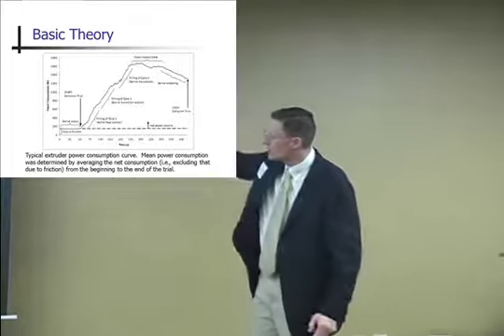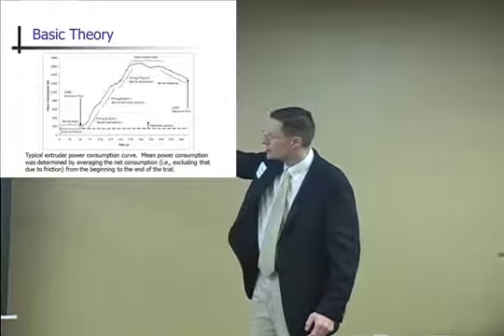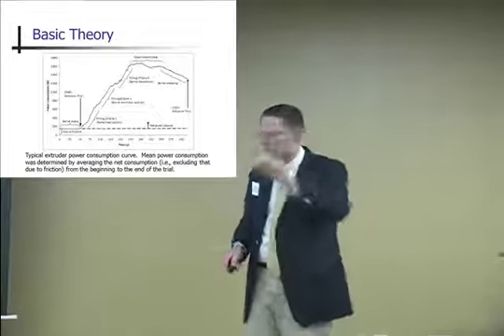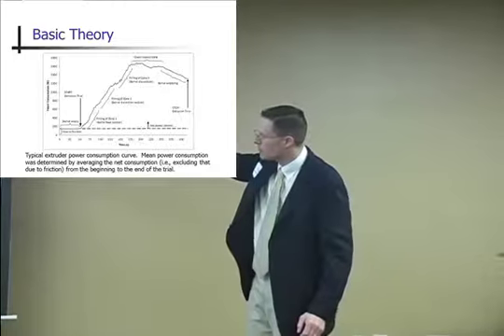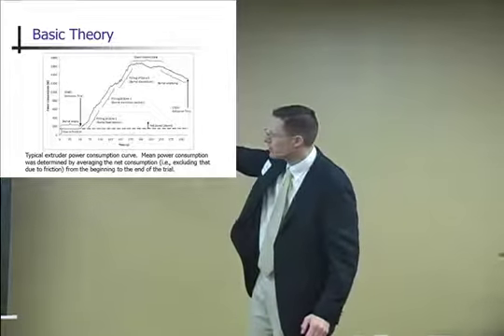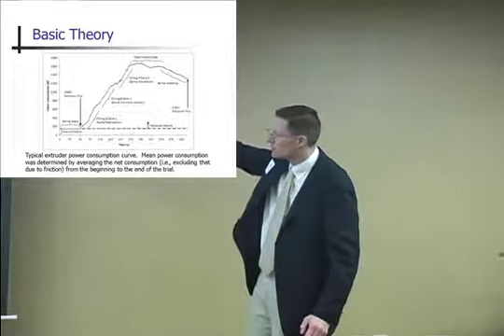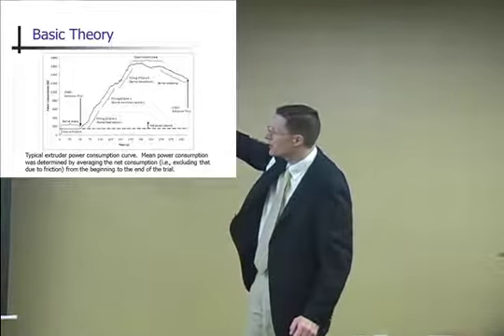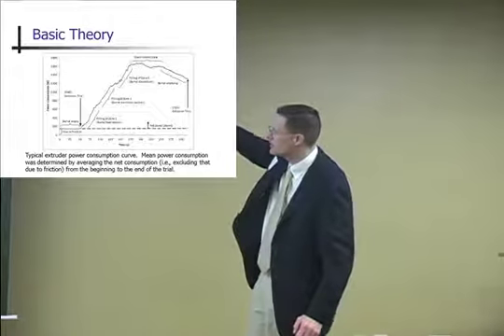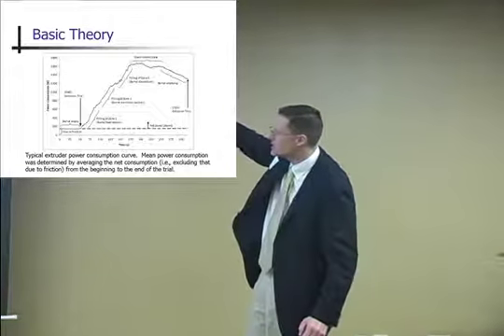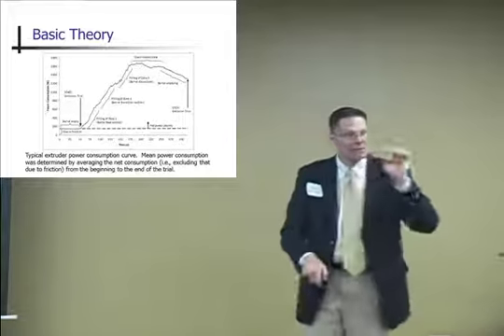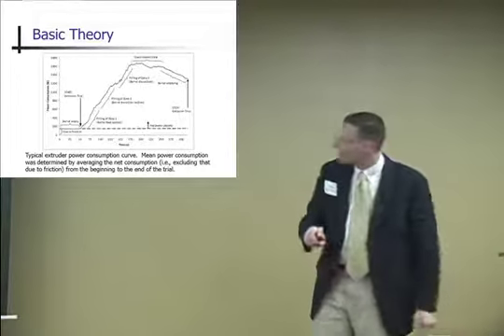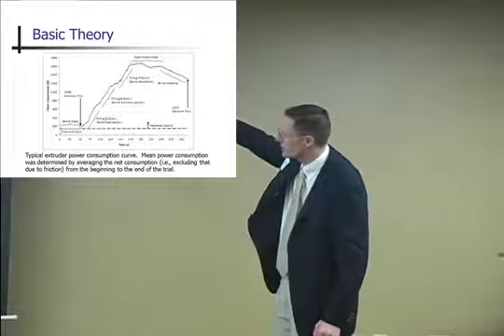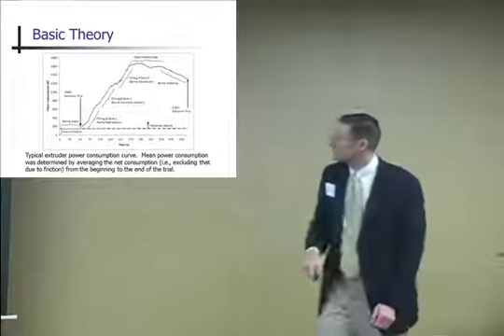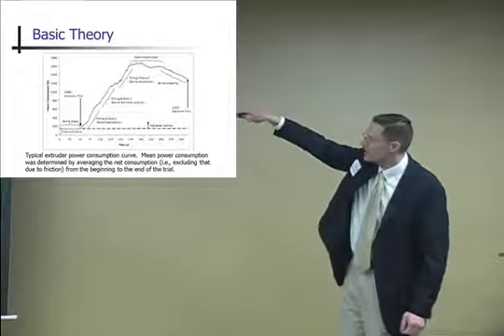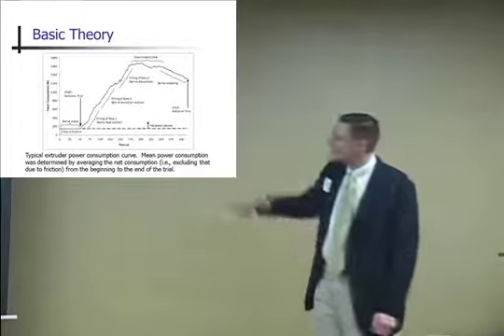So when we started dumping the ingredients in, power consumption increased because we're trying to move that material down. We hit a hanger bearing, so this is chamber 1 or zone 1. The trajectory of that power increase changed. We're filling zone 2. Hit another hanger bearing, entered zone 3. We didn't run the experiment very long, but this is the effective power consumption as you're moving that material when that extruder's full. And then as the barrel started to empty, it would decrease. So this is the area, the sweet spot, if you will, where you're processing. This is your power consumption.